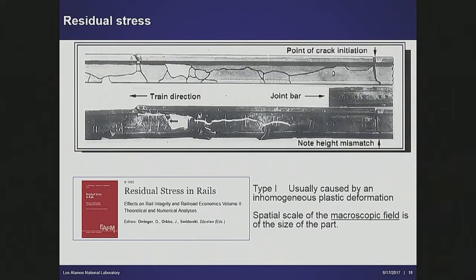But the lifetime of any particular piece of rail relates to whether it's on a curve, how much friction, whether it's lubricated, grinding, temperatures, how well it's supported underneath. And all of those things matter as it relates to, for example, fatigue cracks propagating through the rail. But another big part that affects whether or not something's going to fail is the residual stresses that you get in the rail. So when you fabricate rail, you get residual stresses of the sorts that you now are qualitatively familiar with.